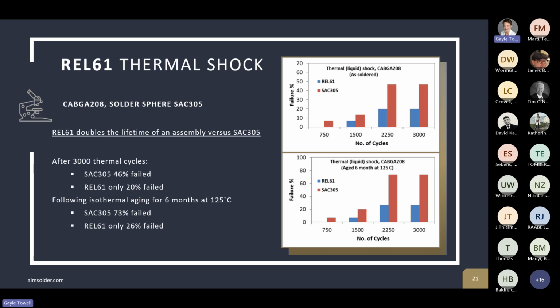After isothermal aging for 6 months at 125 Celsius, same test performed. We have 73% failure in the SAC305 after 3,000 cycles, but only 26% for the REL61.